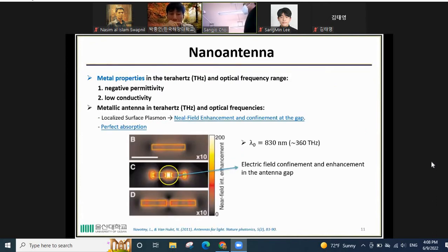So I will explain first about the nano antenna. As we know, metal in the terahertz and optical frequency range has a negative permittivity and low conductivity. So an antenna in the terahertz and optical frequency range also has near field enhancement and confinement at the antenna gap because of the localized surface plasmon. And also the nano antenna shows perfect absorption of the incident wave. So we can see this is the electric field enhancement distribution. We can see that electric field confinement and enhancement happens in the antenna gap at 830 nanometer.